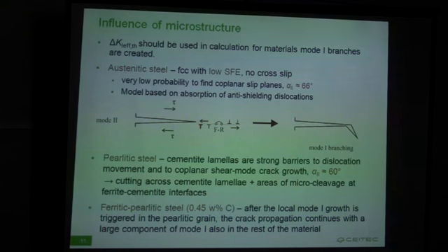And the model of absorption of dislocations generated inside the material described this behavior, because according to this model, when the stress field of the dislocation and the crack tip overlap, it produces crack extension most effectively under opening mode, because there is a nanoscopic decohesion of the material.